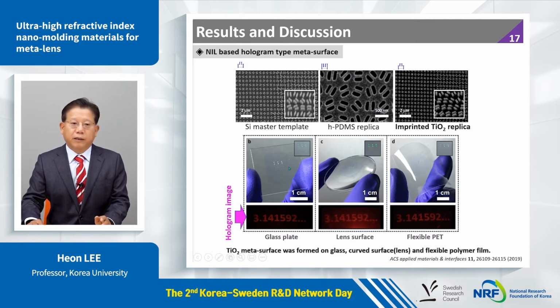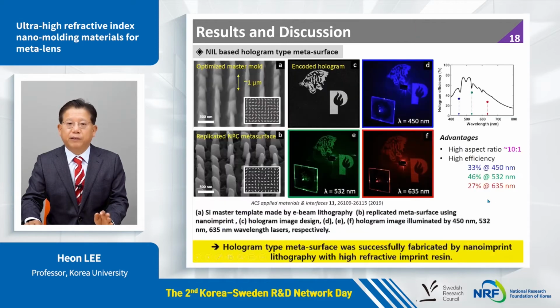This is the metalens formed on a glass substrate. This is the metalens formed on a conventional lens. And this is the same thing formed on a flexible polymer substrate. The bottom one is a hologram image. So it clearly shows that the titanium oxide metasurface was formed very well on a curved glass surface such as a lens, and on a flexible polymer film.